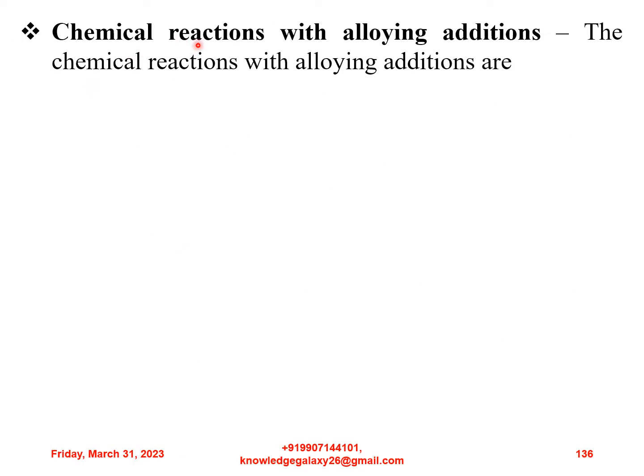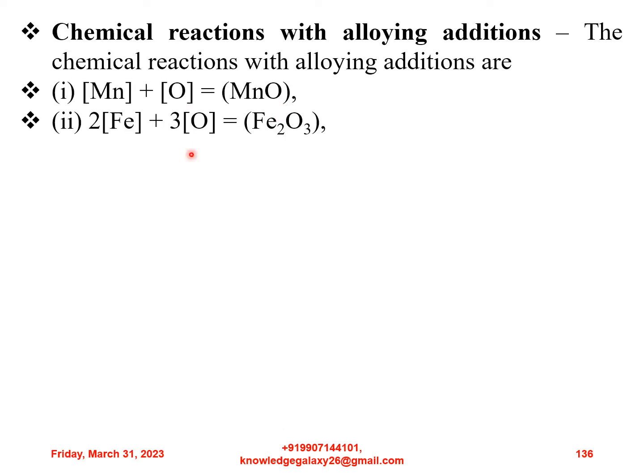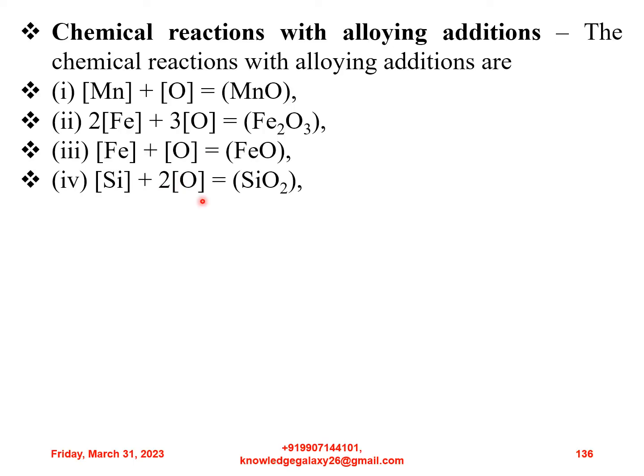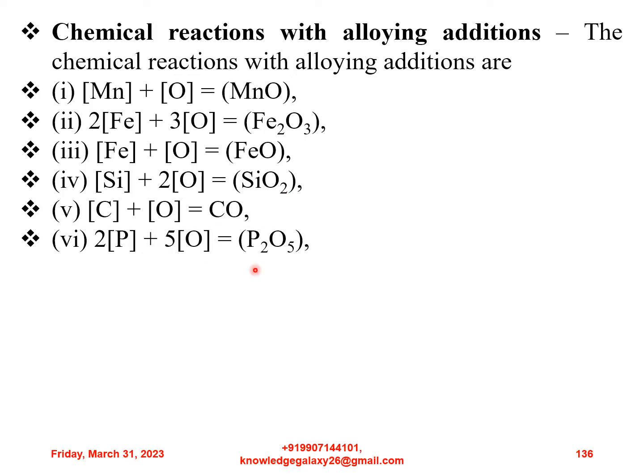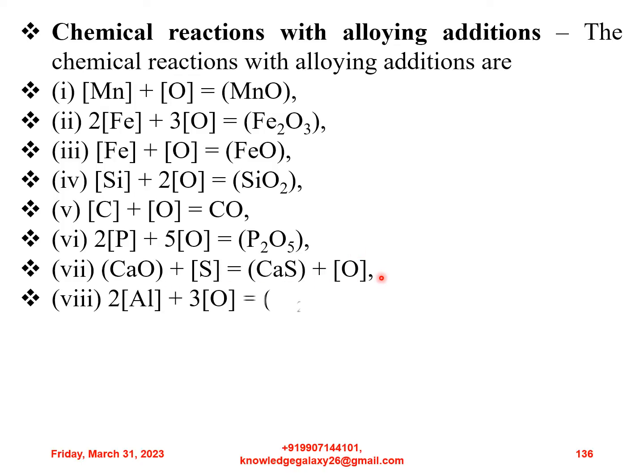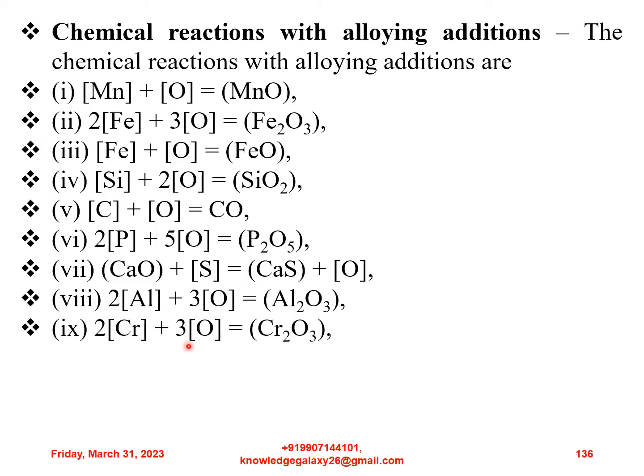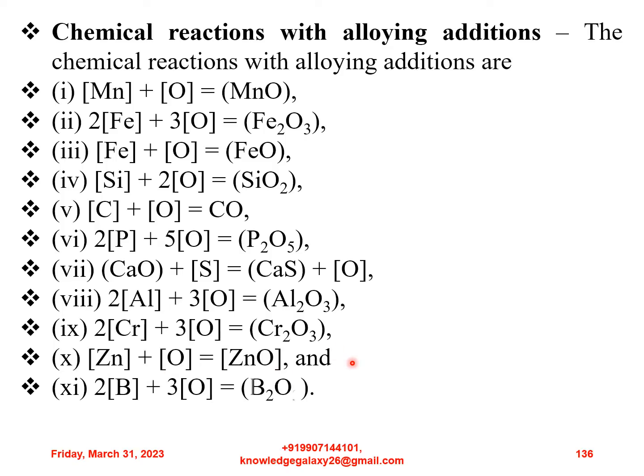Now considering chemical reactions with alloying additions, the chemical reactions with alloying additions are first Mn plus O, this gives MnO, 2Fe plus 3O, this gives Fe2O3, Fe plus O, this gives FeO, Si plus 2O, this gives SiO2, C plus O, this gives CO, 2P plus 5O, this gives P2O5, CaO plus S, this gives CaS plus O, 2Al plus 3O, this gives Al2O3, 2Cr plus 3O, this gives Cr2O3, Zn plus O, this gives ZnO, and 2B plus 3O, this gives B2O3.